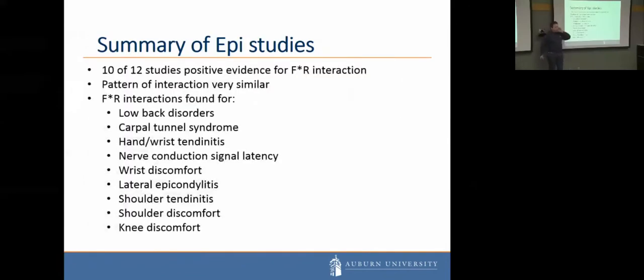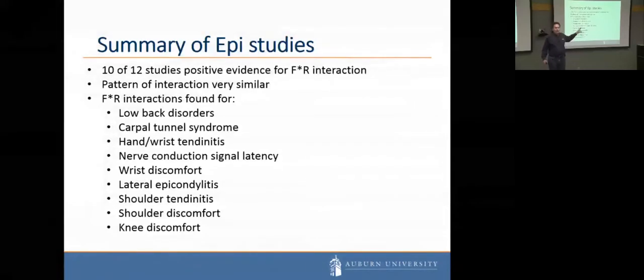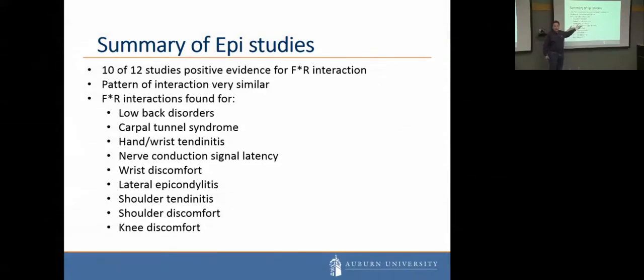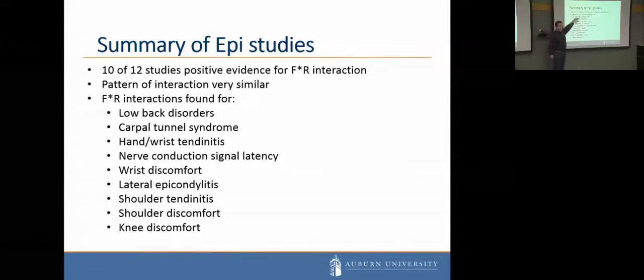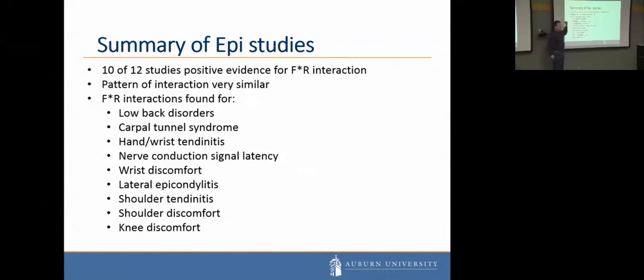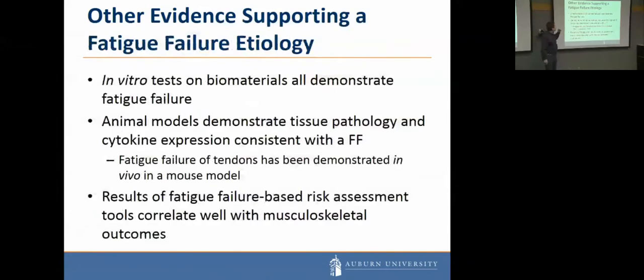So we actually found 12 studies that looked at epidemiology, including a force by repetition interaction. And these were either studies that were published or where we could get the data and actually do the analysis ourselves. We found very similar patterns of interactions, and we found it for low back disorders, carpal tunnel, hand wrist tendonitis, nerve conduction signal latency, which is a test for carpal tunnel syndrome, wrist discomfort, lateral epicondylitis, shoulder tendonitis, shoulder discomfort, and knee discomfort. So that covers a whole lot of joints there. I won't get into that.